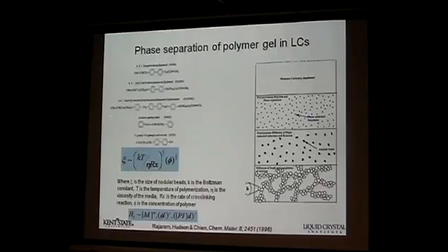So with this type of material, they are the rod-like shape. They have a functional group at the end for forming this network, and then you need a small amount of this photoinitiator, and certainly you need a liquid crystal host. This host can be nematic, smectic, chiral smectic, banana, cholesteric, blue phase, anything you were thinking about, or maybe lyotropic nematic like disodium cromoglycate, the DSCG, forming this lyotropic nematic.